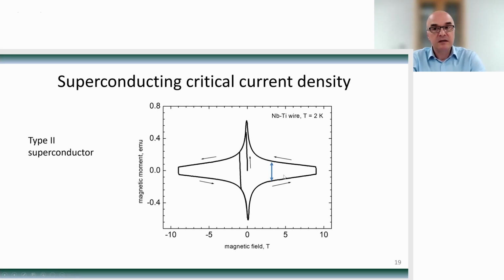There may be difficult mathematics to relate the experiment to the precise geometry of the sample if the geometry is complicated. But the field dependence of the critical current and temperature dependence of the critical current can be immediately obtained from a set of measurements like this.